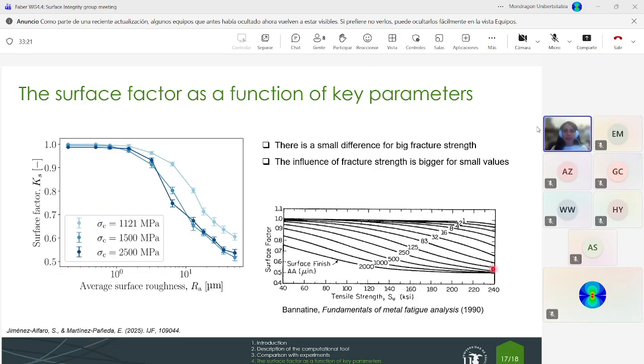Maybe now you ask yourselves how we determine this fracture strength, and we use the phase field model. We just fit our SN curve of the polished specimen. By doing this, we fit what is called the phase field length scale. This is related to the fracture strength, and then we ensure that this fracture strength is just bigger than the tensile strength.